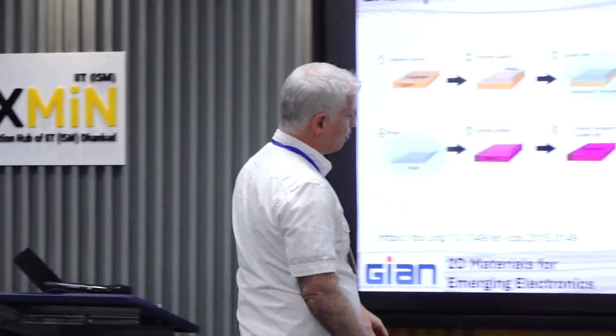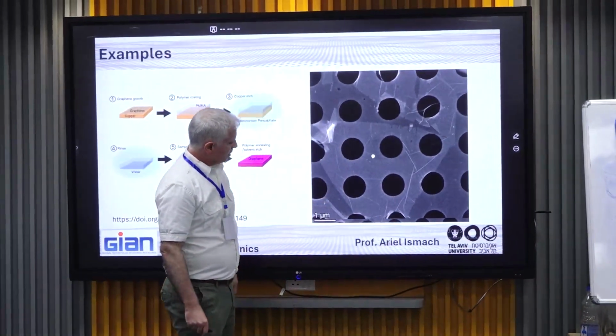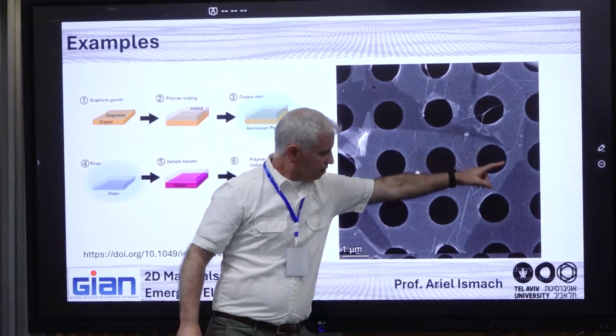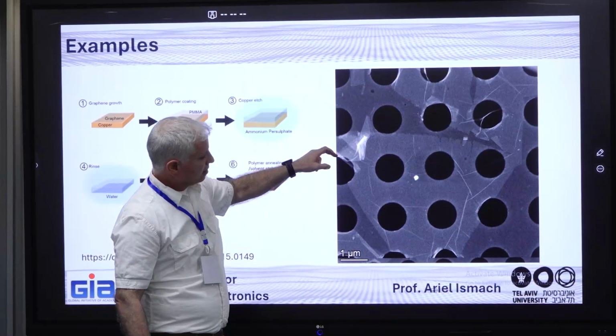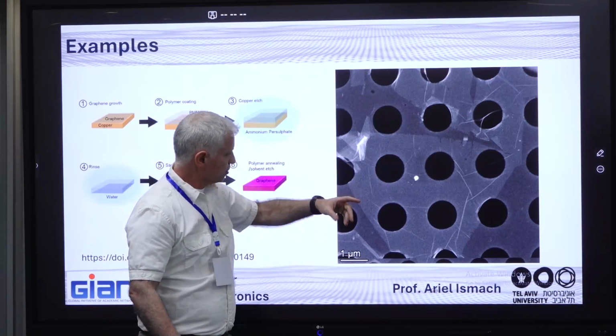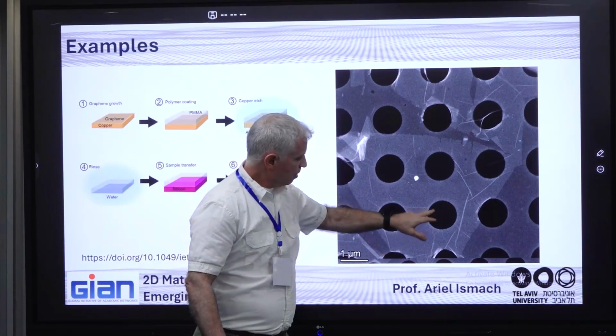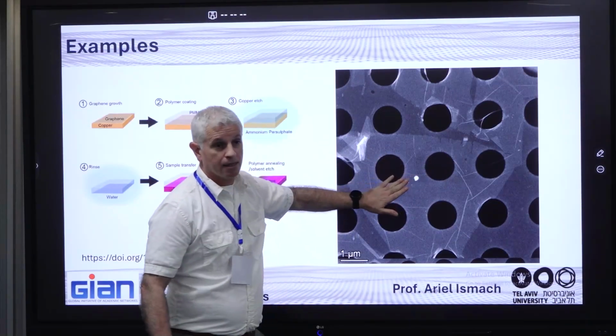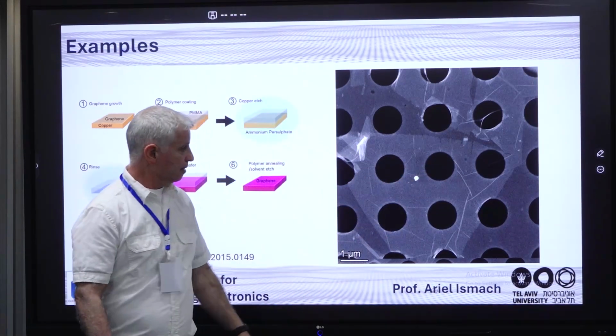But then, of course, as you may imagine, these TEM grids are very thin and very sensitive. You need to be very careful, and the success yield in transferring atomic layers to these TEM grids is not always great. You need to practice a lot. Here you can see an example of a grid. I think it's a silicon nitride grid, and what you see here are domains of tungsten disulfide. You see that sometimes they just break, fold, and then you have some areas. These areas are covered by a single atomic layer, so a single-atom-thick membrane.